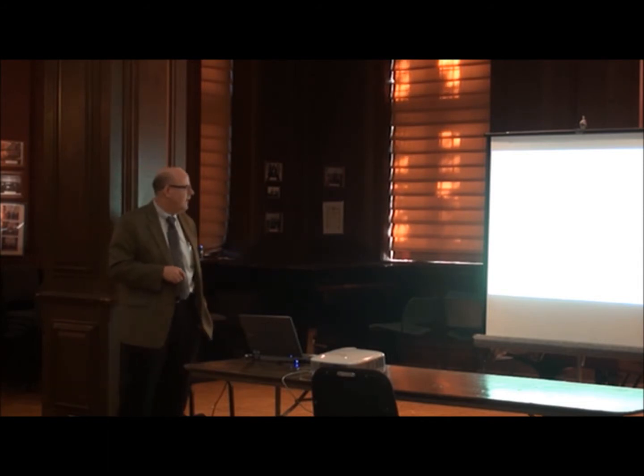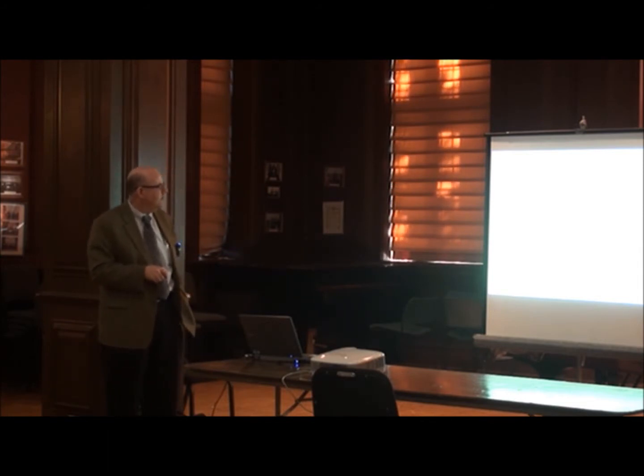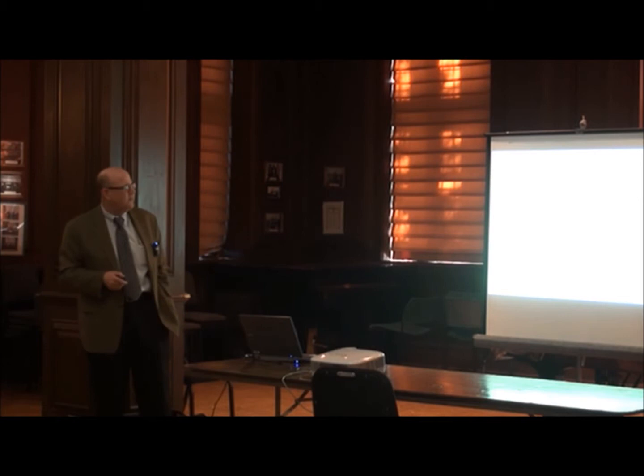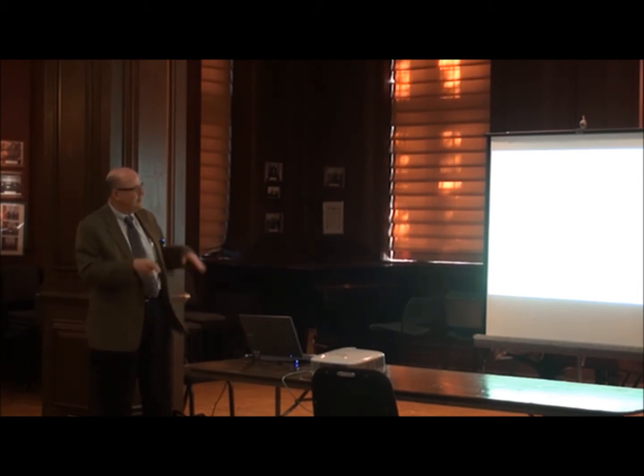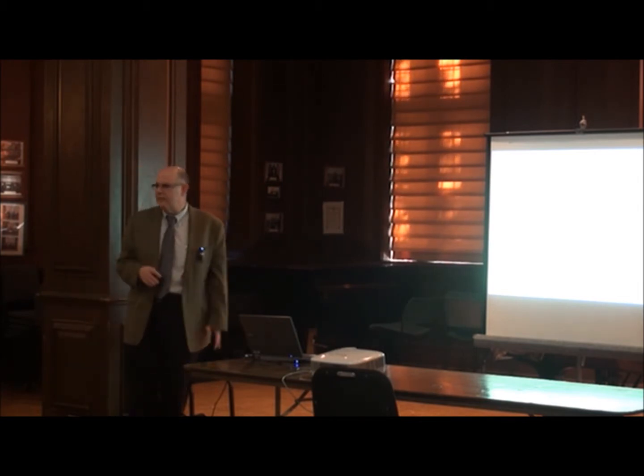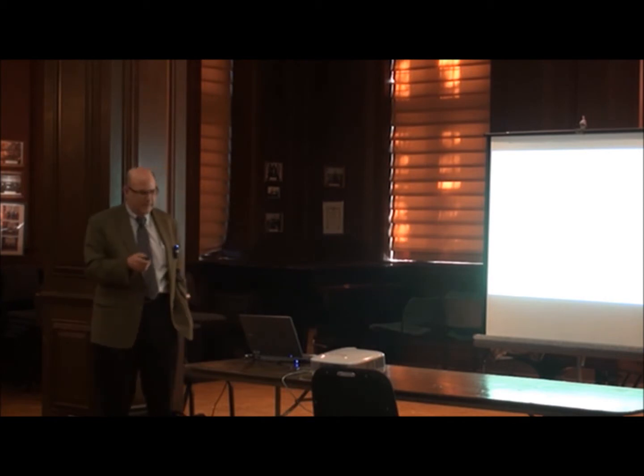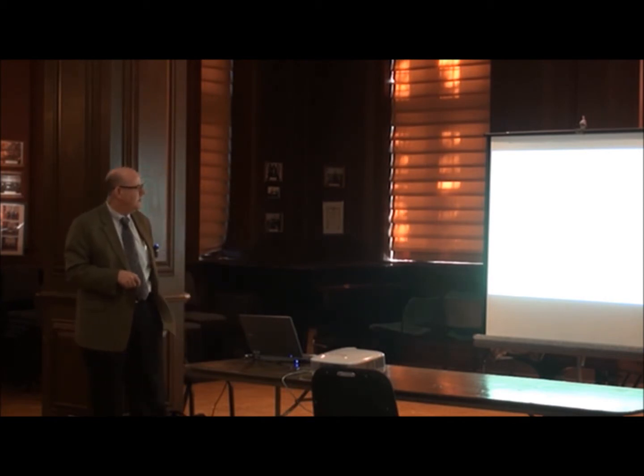If all of a sudden I plateau the surface and put some dents into it, now the skew gets highly negative, the RMS roughness increases, and the kurtosis gets larger. As a result of this, I'm changing that symmetry. You'd expect I would change the real area of contact. And indeed, that's been demonstrated by some work.